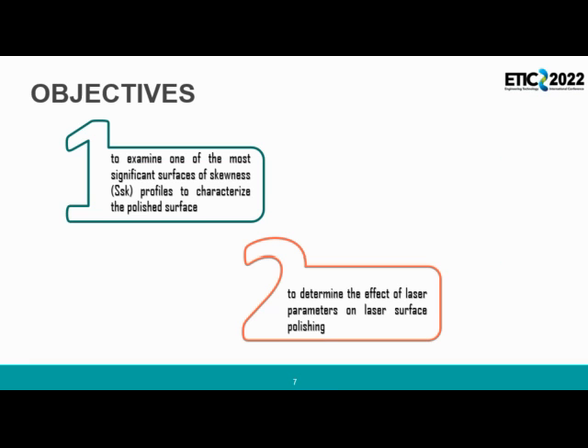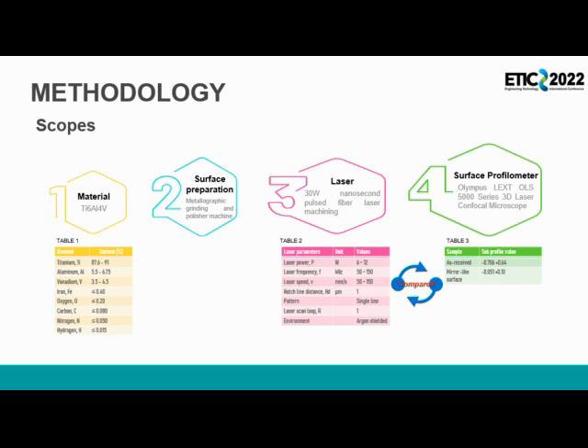Similarly, the surface profile of skewness will also ideally be able to flatten the surface by lowering the value of skewness. In the case of laser polishing, all peaks and valleys are flattened by the laser. This paper aims to examine one of the most significant surface profiles, which is skewness, to characterize the polished surface. The effect of laser parameters involved in surface polishing has also been discussed.